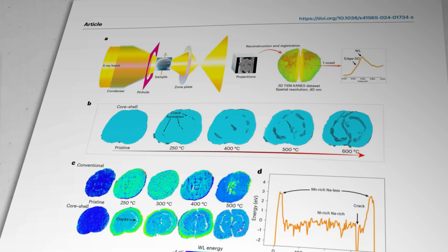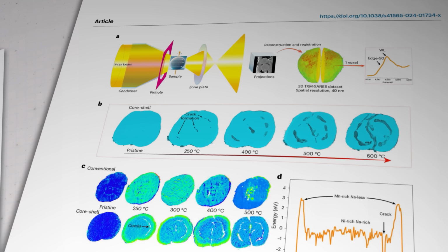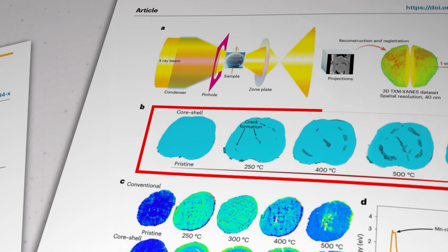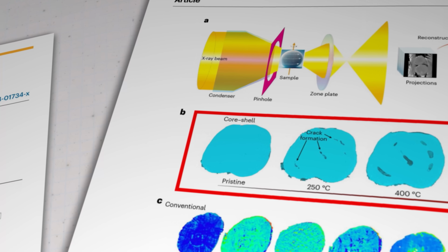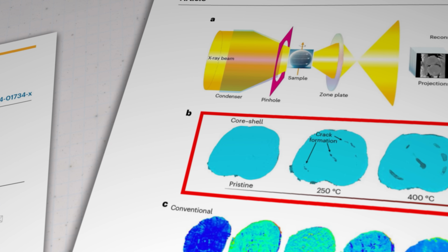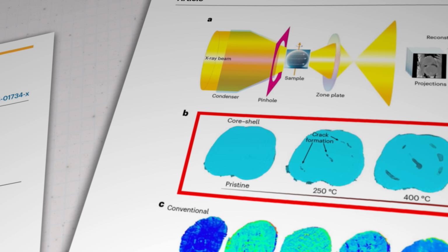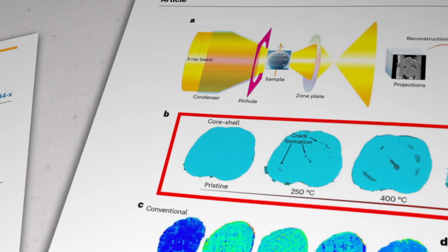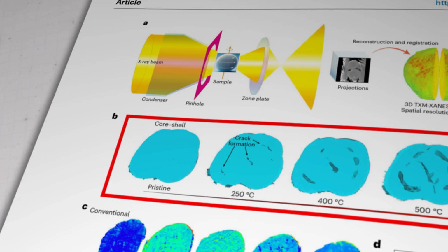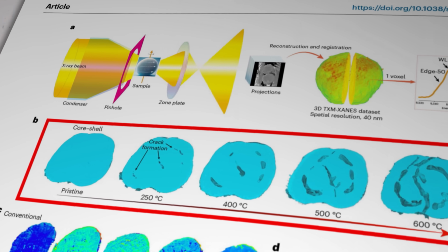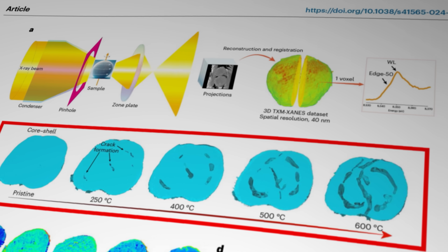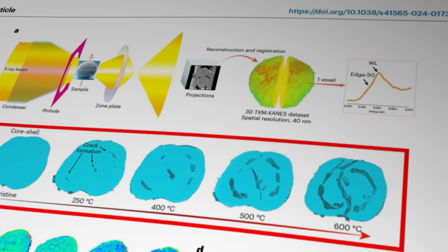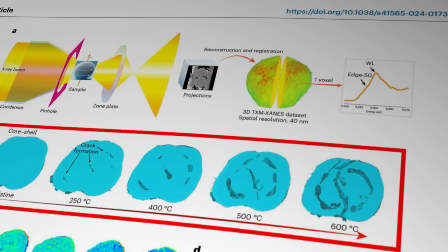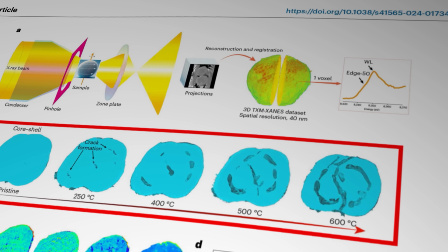In the sample with the gradient metal configuration, cracks were forming at around 250 degrees Celsius, but instead of starting at the surface and spreading inwards towards the core, which is what generally happens during the electrochemical process of charging and discharging a battery cell, those cracks were actually starting deep inside and spreading outwards. By contrast, in the sample with evenly distributed metal, cracking was barely observed at all.